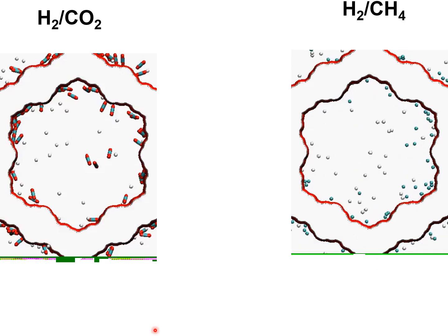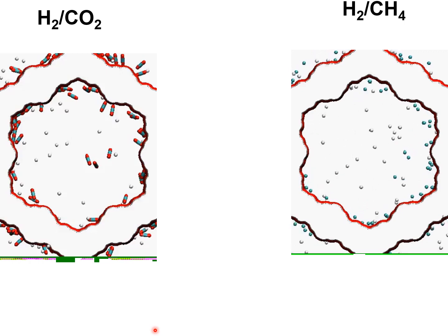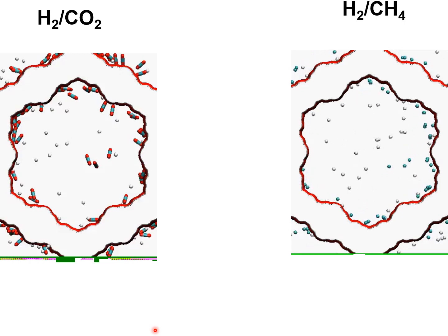I think the message that has been obtained from these MD simulations is that the higher the adsorption strength, the higher is the concentration of any gas molecule near the pore wall, and the Knudsen formula for molecule-wall collisions becomes increasingly inaccurate for molecules that have high adsorption strengths.